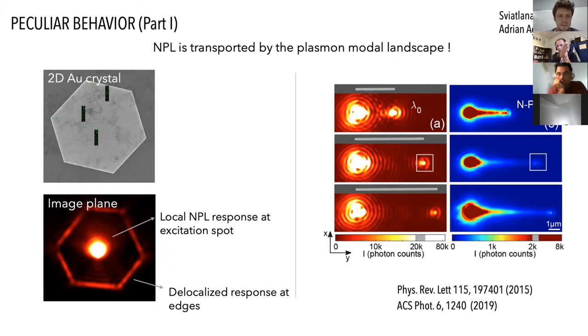So the electron temperature is higher where the plasmon is born, and it's lower when the plasmon dies. And during all this period, you have this emission, the radiative fate of these hot electrons, which is reminiscent of the electronic temperature, basically. So I agree with you. The surface plasmon is a source of the heat, but not the heat of the lattice, the heat of the electron temperature.